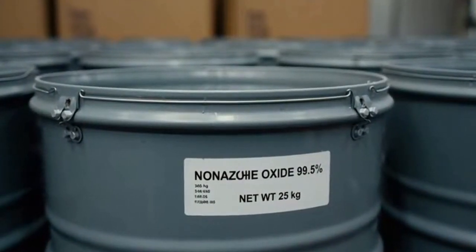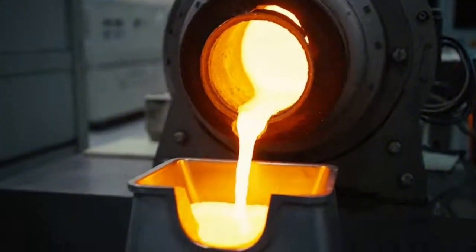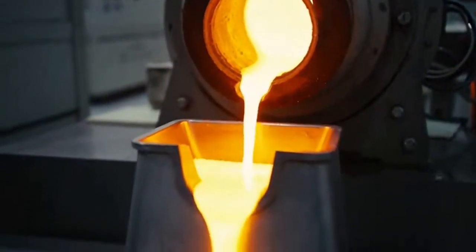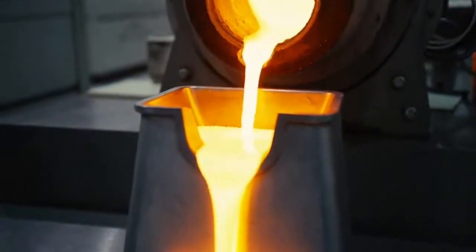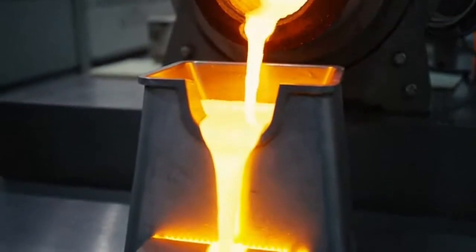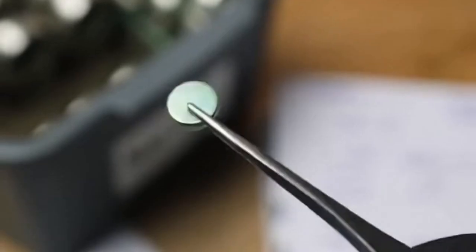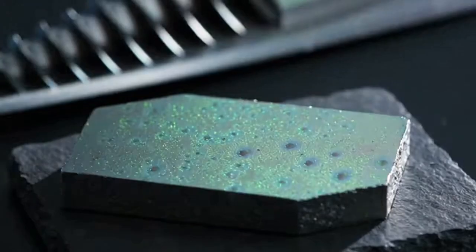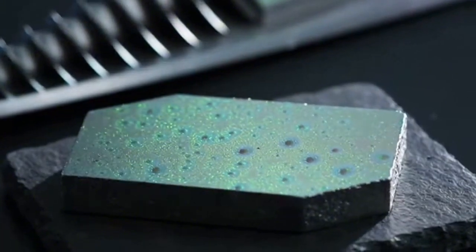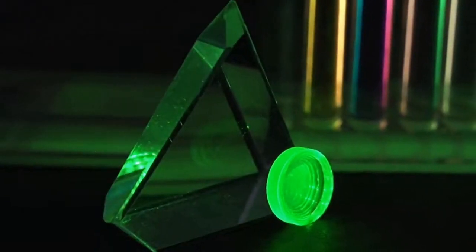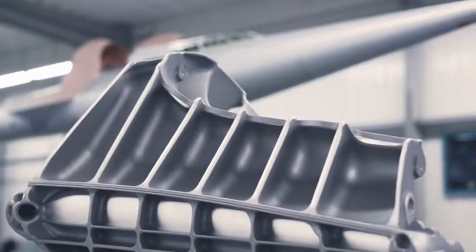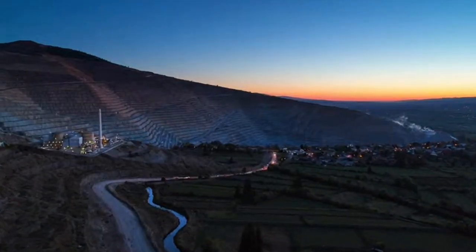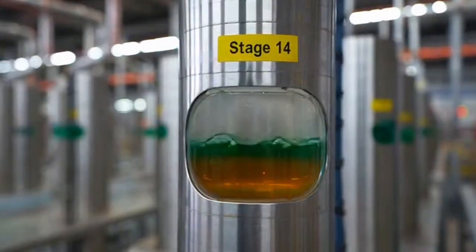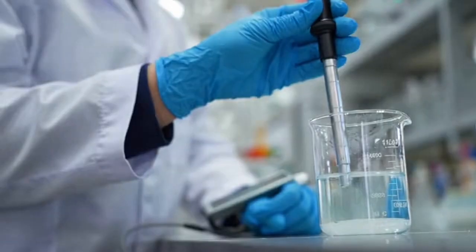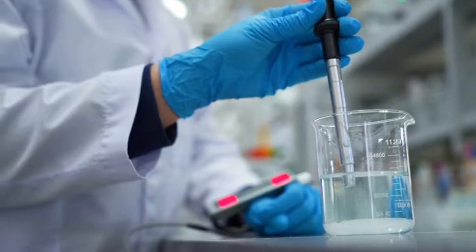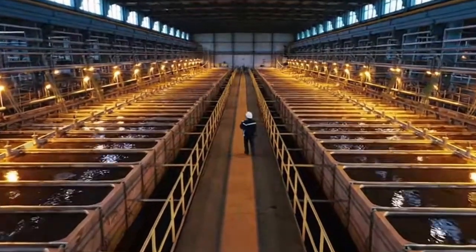Praseodymium's role in this choreography is not to steal the show, it is to tweak the script. In the neodymium iron-boron structure, swapping some neodymium for praseodymium shifts the magnetic anisotropy and the temperature coefficient of coercivity by amounts that engineers care about in the real world. You are trading a little saturation magnetization here against a little thermal stability there, and those microtrades determine whether your inverter throws a fit when you push a car up a long grade in summer.